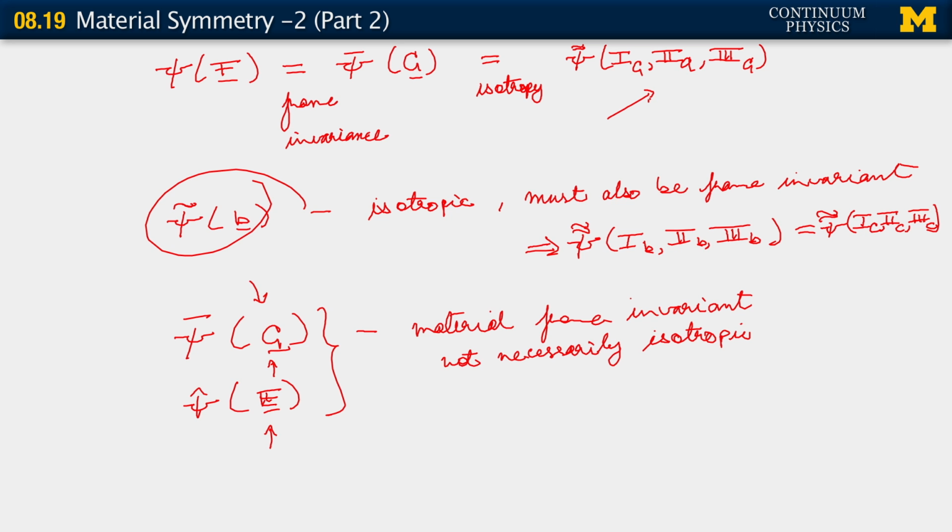It's isotropic. For general materials, single crystals, anything that actually reflects crystallographic structure, or fiber reinforced composites, all of these can be general functions of C or E. And then, of course, the question of how good a model it is for the particular composite or the particular crystal we are trying to model depends upon how well we pick these functions of E or C. All right, so we better end this segment here.